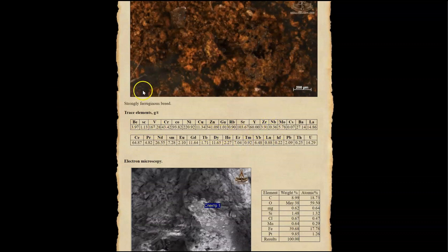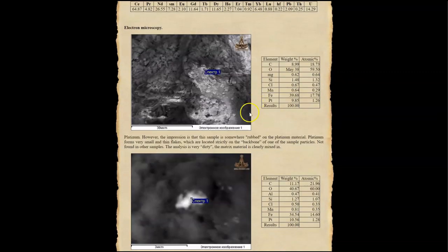No macro element composition, but the trace elements are listed here, and this sample is mostly iron just like all of the rest. And now, some very interesting electron microscopy here, with a 39% iron sample with almost 10% platinum, which is described here as the impression is that the sample is somewhere rubbed on the platinum material. Platinum forms very small and thin flakes, which are located strictly on the backbone of one of these sample particles. Not found in other samples, the analysis is very dirty, and the matrix material is clearly mixed in.